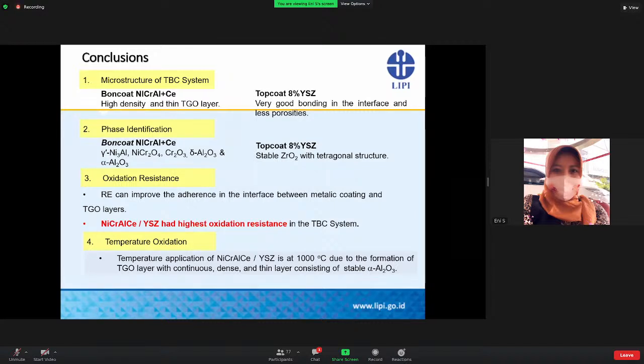According to the microstructure of the TBC system from the bond coat of the coating samples, it shows a high density and thin TGO layer, while the top coat of 8% yttria stabilized zirconia has very good bonding at the interface and less porosity. And according to the phase identification, the bond coat consists of gamma prime, spinel structure, chromium oxide, and metastable alumina. For the top coat, there is only a single tetragonal structure of zirconium dioxide.